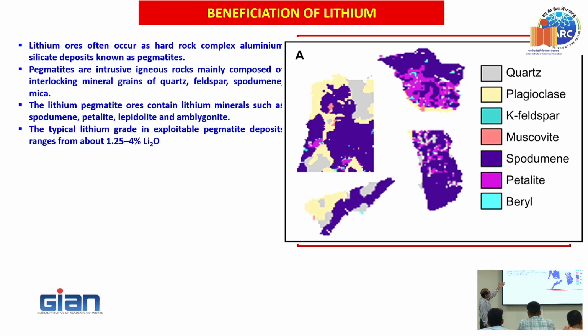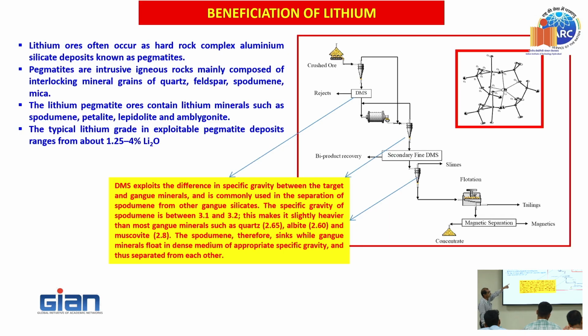The lithium pegmatite ores contain lithium minerals such as spodumene, and then it also contains quartz, feldspar, and so on and so forth. Now, how do we do the beneficiation? This is the beneficiation flow sheet, a generic one, which we follow for spodumene based materials. You have the ore, you crush it, then use the dense media separators. In the dense media separators, DMS exploits the difference in the specific gravity between target and the gangue minerals. It is commonly used and industrially used in the separation of spodumene from other gangue silicates. For example, the specific gravity of spodumene is between 3.1 and 3.2. This makes it slightly heavier than the gangue minerals like quartz, albite, and muscovite.